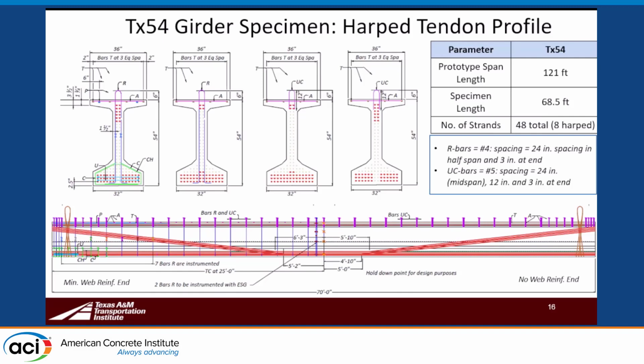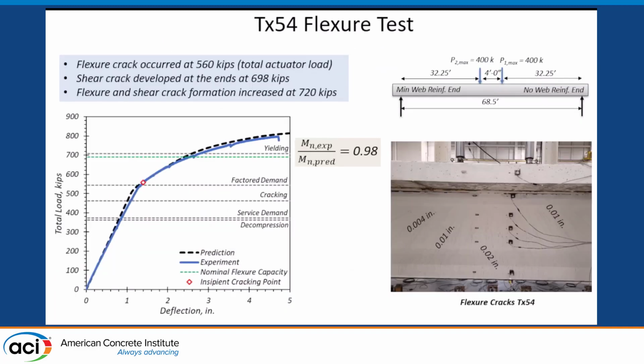Because we went to just minimum reinforcement here, so 24-inch spacing, that's not as closely spaced as typically done in conventional girders. That might be more like 6 to 12 inches. So we are supplementing that with what we're calling UC bars. And these UC bars are 180-degree hooks that, on one half of the span, we are adding 2 of to each R bar. And at the other side, we don't have any R bars, no web mild steel, but we do have these hooked bars in bundles of 3. So we're trying to put in enough strength for interface shear transfer, and they're spaced far enough apart to help with the casting.